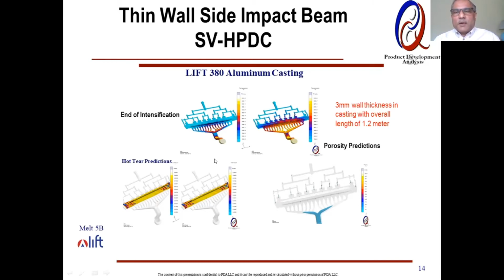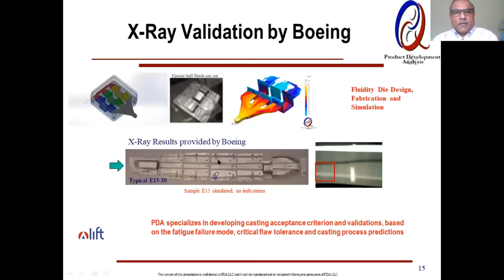And we took a part which is the side impact beam of an automotive company, about 1.2 meter long and 3 millimeter wall. At some areas, we had almost close to a 1 millimeter wall, and it was a challenge to come up with the process parameters and the gating system to make sure it fills in without any hot tear or porosity in the critical areas. So we were able to successfully simulate, and Boeing went back and validated through extensive X-ray, and they found sound